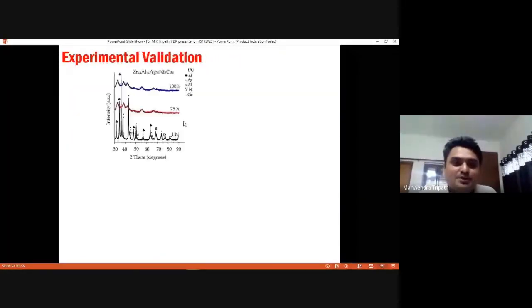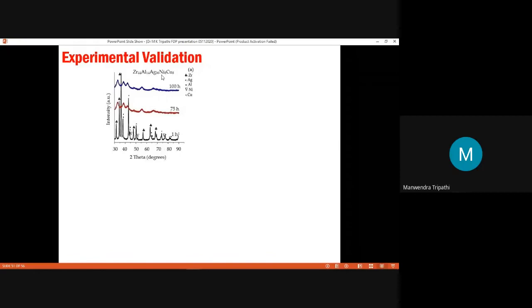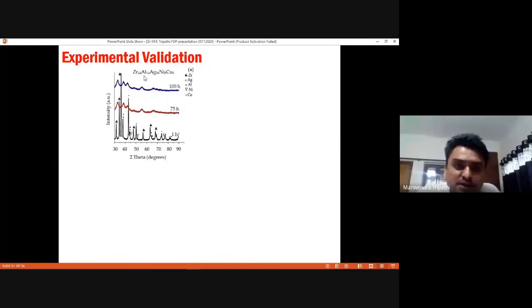So we have gone for mechanical alloying, and this is the composition. We have taken zirconium, aluminium, silver, nickel, and copper powders, and we have done mechanical alloying. In mechanical alloying, there is a possibility of alloy formation, right? This is one of the ways. We are not making the glass directly, but indirectly we are checking the amorphization potential of that composition. So when we mill it for 1 hour and do XRD, these are the crystalline peaks we get.